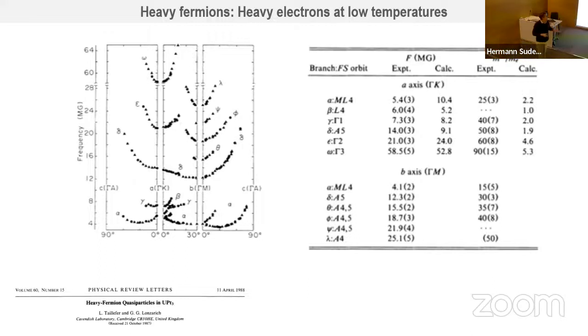Now, you may make calculations and you may calculate the effective mass, for example, here, and you may compare with what you find here. And actually, even if the geometry which you get is correct, the effective mass is completely wrong by 2 orders of magnitude.